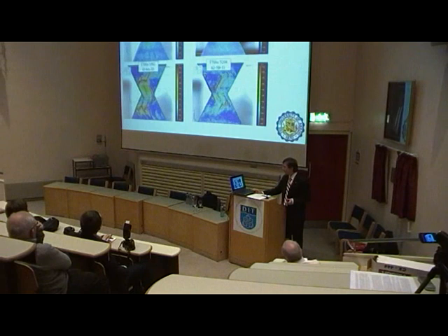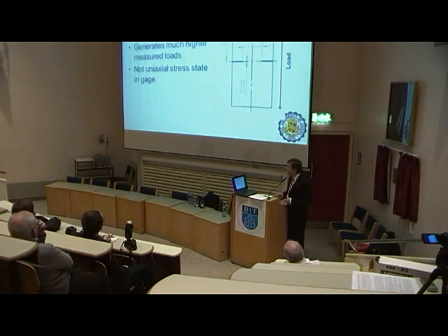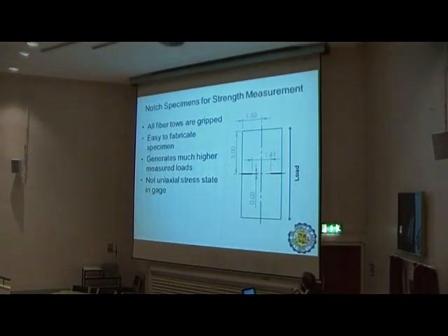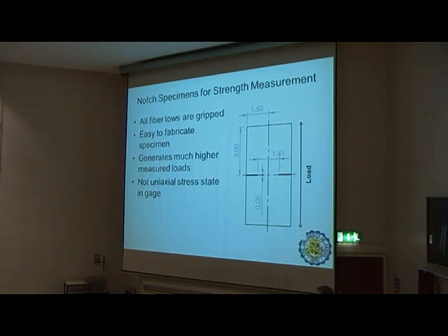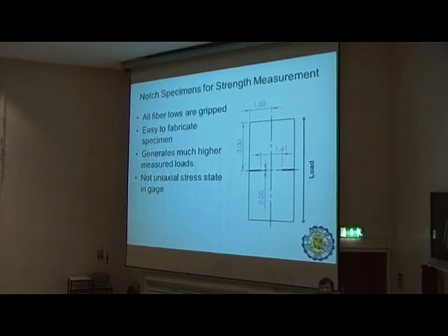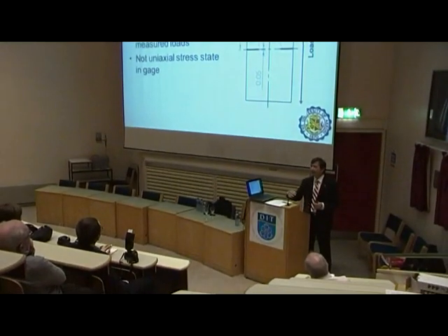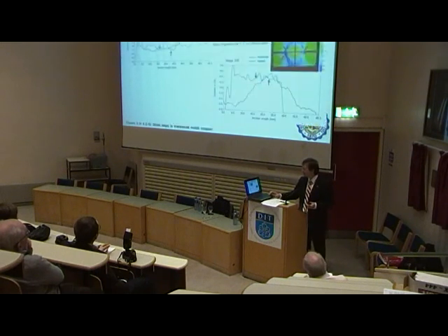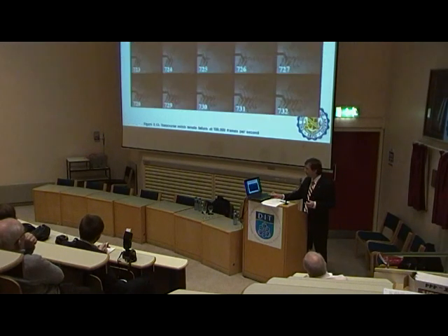These are tons of tests, so I'm not going to spend too much time. We developed a modified tensile specimen with two slots here. The idea is that those bundles that come through the gauge area of the test will be embedded in the rest of the material. Therefore, you will not create those edge effects, and therefore get results closer to the test. However, we found that this has a consequence of testing locally under biaxial loading conditions, not uniaxial,